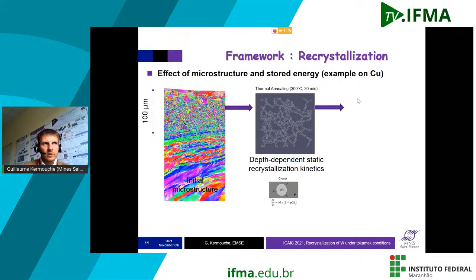And here you have an example of what happens in a microstructure with a gradient inside. This is a microstructure that has been obtained with severe plastic deformation, but with some shear. So the plastic deformation was very high here and a bit lower here. You can see that there is a gradient of microstructure. Here you have a huge grain size with some disorientation inside. It is on copper and not tungsten, because we cannot do that on tungsten.